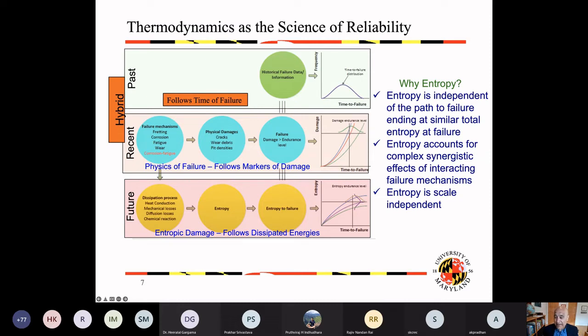Entropy accounts for complex synergistic effects. So when I have entropy of corrosion and entropy of fatigue, both of them have the same measure, which is entropy. It's not like the physics of failure, where markers of damage are very different in a crack and very different in corrosion. Entropy is the same measure for corrosion, for fatigue, for wear, for creep, fretting, everything.